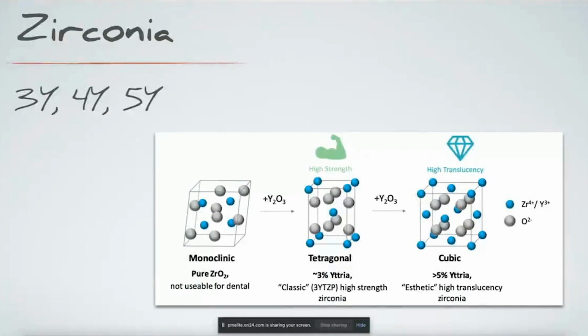But then more recently, some of these more highly translucent aesthetic zirconias have started to come out. I'm sure people here are familiar with something like Katana. And that is more in this kind of 5% type of yttria. So high translucency for sure. But as we start moving toward that high translucency aesthetic zirconia, we start losing that strength that we all kind of love of zirconia. So we start moving away from that minimal prep of 0.8 to 1 millimeter because we're having to build up that thickness again to accommodate for the aesthetics or the translucency that we're trying to get. And that to me is where 3M's Chairside Zirconia has really become this nice blend of beauty and the strength that we want from zirconia.